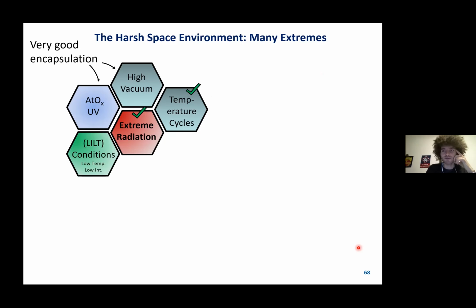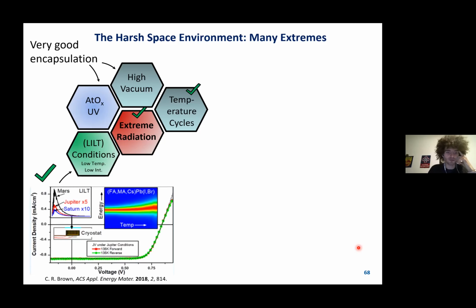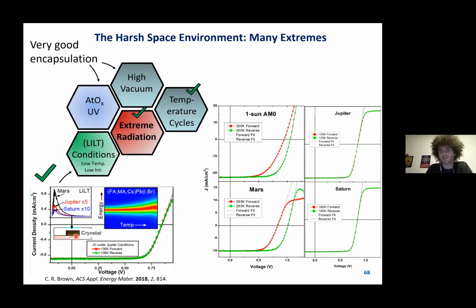But then you can have very low intensity, low temperature environments. And here are some very nice results from Brown et al. Here from Oklahoma. They looked at formamidinium, methylammonium, cesium, lead, iodide, bromide perovskites at different temperatures, so using a cryostat. And they tested them under a variety of different illuminations as found on Jupiter, Saturn, or Mars. And their results were super promising. The perovskite worked very well in these low temperature environments, where actually III-V semiconductors, again, already would be very poorly performing. However, it also depends on the perovskite composition.